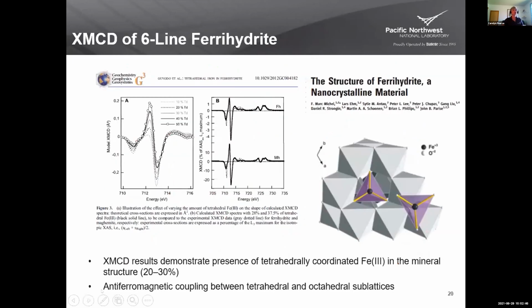There have been some studies that have looked at ferrihydrite using XMCD. This is one example looking at 6-line ferrihydrite, which is slightly more ordered than 2-line ferrihydrite. And this work really demonstrated from the magnetic component that you could see a tetrahedral iron 3 contribution, and that the magnetism comes from antiferromagnetic coupling between those tetrahedral and octahedral sites.